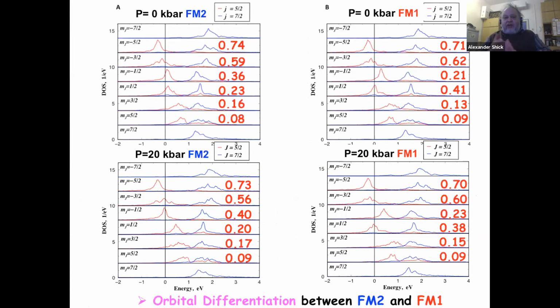Okay, we wanted to look into the microscopic reason for that. And for this reason, I plot the F projected densities of states on the uranium atom. I resolve them into J equal 5/2 and MJ, this is a projection on the easy magnetization axis. So these are 5/2 in red and 7/2 in blue. Then if I compare those for FM2 states at zero pressure, I see there is a change for these -1/2, +1/2 states in the FM2 and FM1 phase. And actually this change becomes even more pronounced when I go to the FM1 state under pressure, in the sense that those electrons which were shared between those states now jump into the state with MJ 1/2. And we call it orbital differentiation between those two phases.